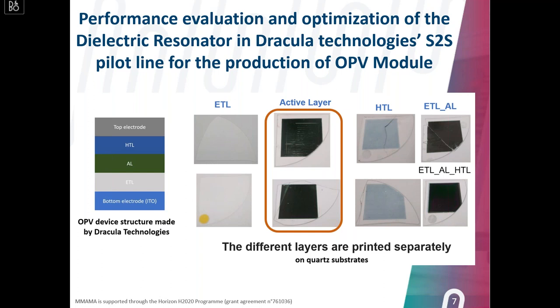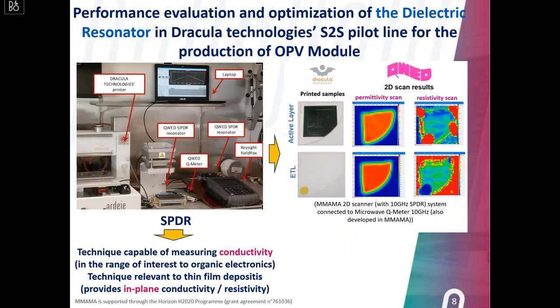So we print several layers under the same conditions as in our OPV modules, to be characterized by QWED with the dielectric resonator. All the samples in this part are printed on quartz substrates. Here are some typical measurements already done by QWED on our printed layers. I took two examples, the active layer and the ETL layer, and here we can see the two-dimensional scan results based on this technique. After integrating this technique in our pilot line, as you can see in the photo, we have our printer, and right next to the printer we have this system for SPDR and SiPDR measurements.